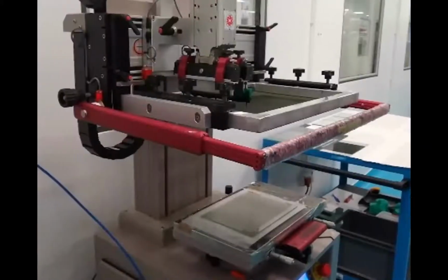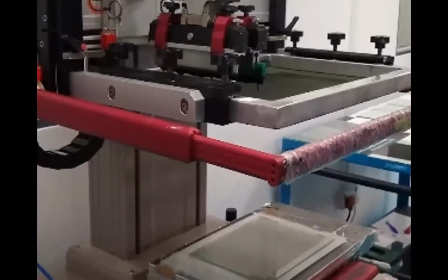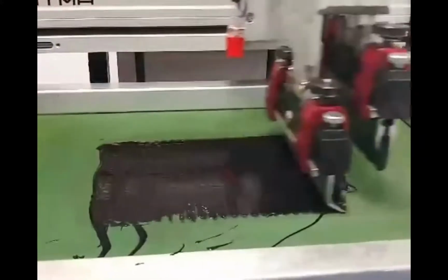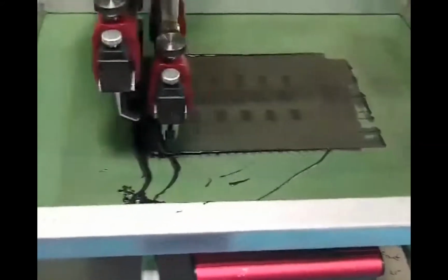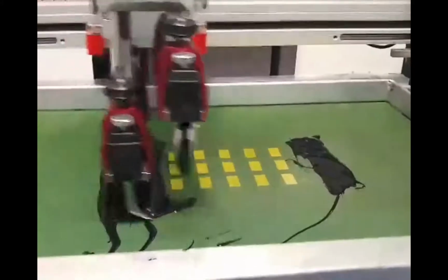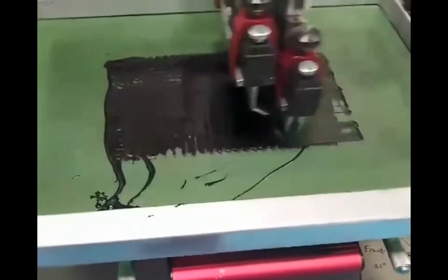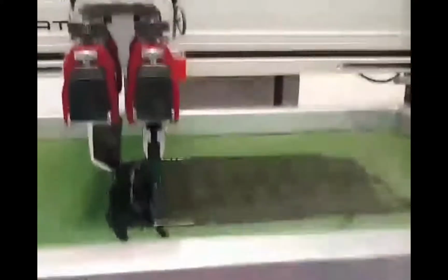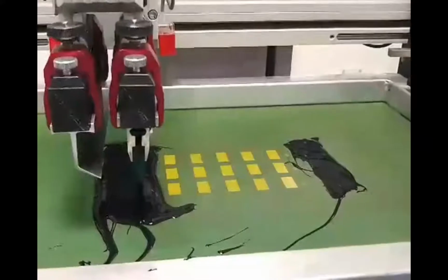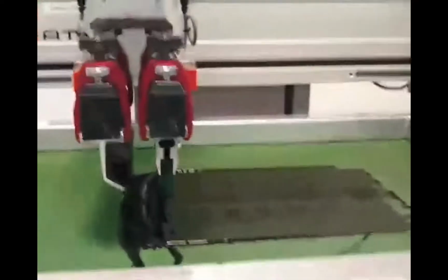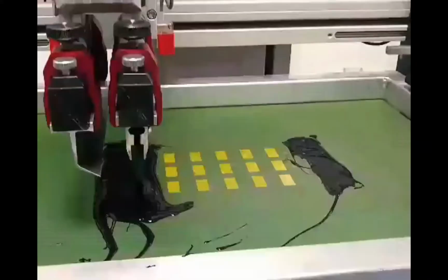Next, the first layer of titania is put down using spray coating, with the glass heated on a hot plate below it. Then the following three layers are put down using screen printing. Screen printing involves a screen with a woven mesh and stencil, which allows the ink to be put down onto a range of substrates. The substrate being printed onto can take the form of a variety of things from glass to t-shirts. As the ink is forced through the holes in the mesh, which aren't covered by the stencil, by the force of the squeegee, first the ink is scraped in as an even layer over the mesh with a steel coater. Then it is forced onto the surface with a polyurethane squeegee, leaving behind the print.